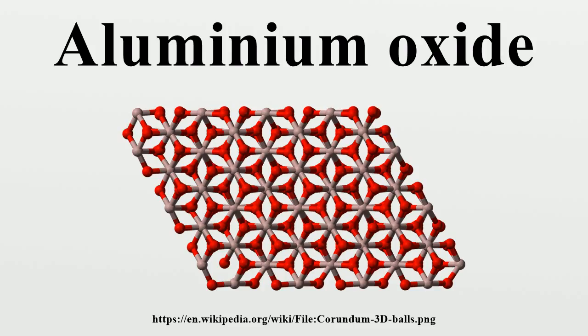Molten aluminium oxide near the melting temperature is roughly two-thirds tetrahedral, and one-third 5-coordinated. Very little octahedral Al is present. Around 80% of the oxygen atoms are shared among three or more Al polyhedra, and the majority of inter-polyhedral connections are corner sharing, with the remaining 10 to 20% being edge sharing. The breakdown of octahedra upon melting is accompanied by a relatively large volume increase. The density of the liquid close to its melting point is 2.93 grams per cc.